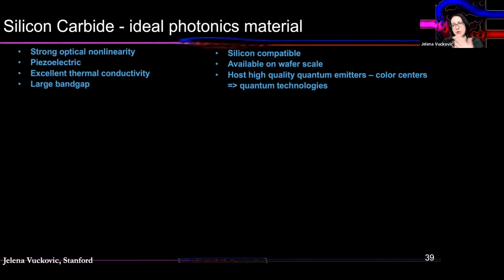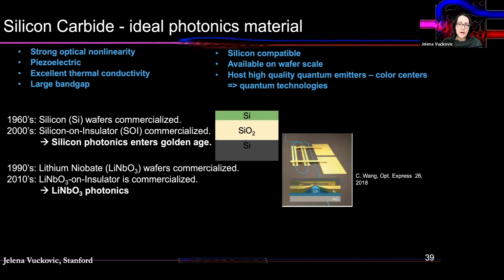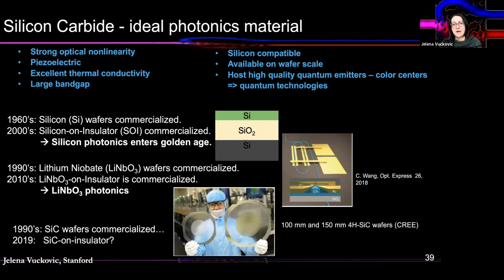And in silicon carbide, we're doing the same thing. I'd like to just remind you, if you're not familiar with silicon carbide, that silicon carbide is a material that is heavily used in power electronics. It's also available on wafer scale, 6-inch wafers in a bulk form. It's much cheaper than diamond, and it has excellent properties for photonics, including second-order optical nonlinearity, which we're very excited about. And these people are of course working a lot on lithium niobate and silicon photonics these days, but none of the other materials offers everything that silicon carbide offers, which is a scalable platform where you can also combine electronics, second-order nonlinearity like what you have in lithium niobate and electro-optical effect, but also offers quantum emitters that have high quality, as I showed you previously.